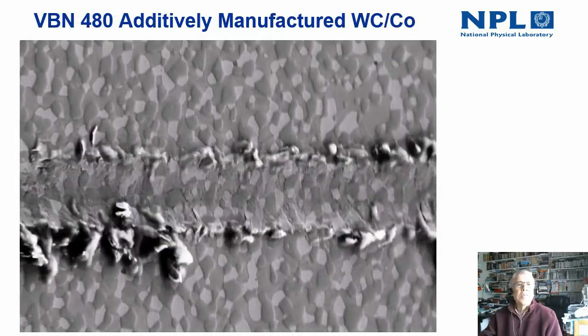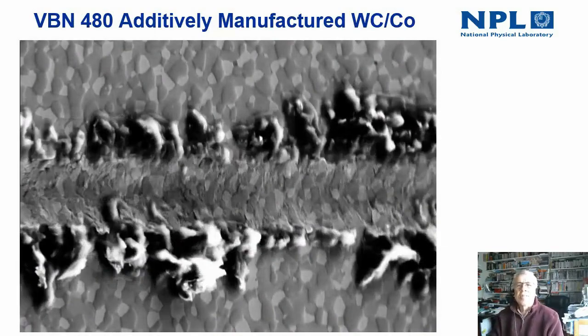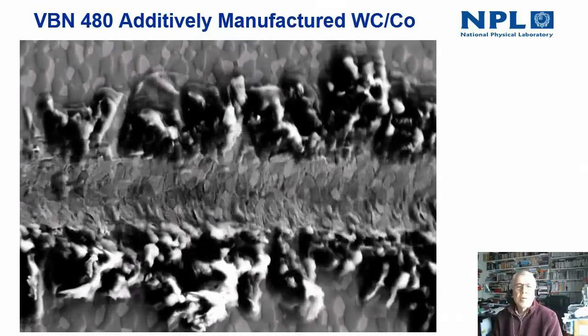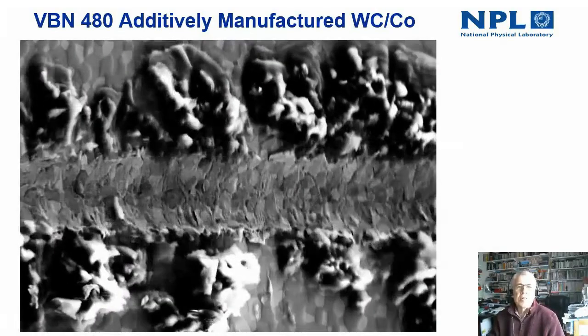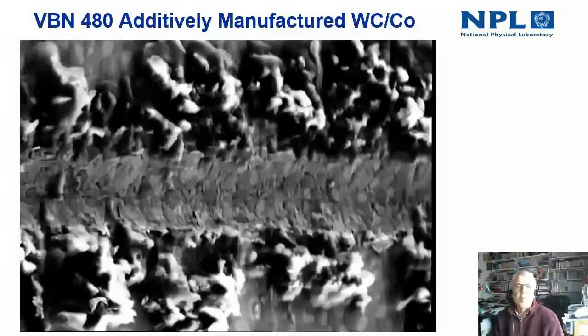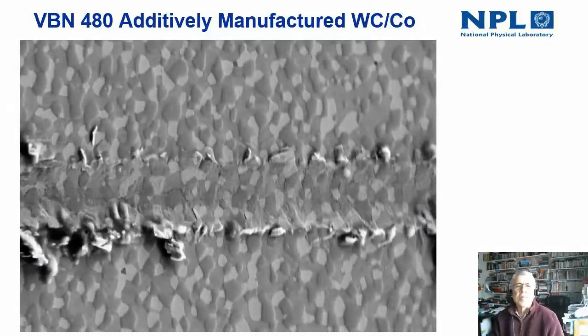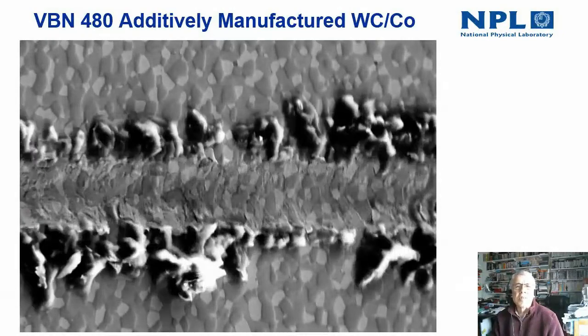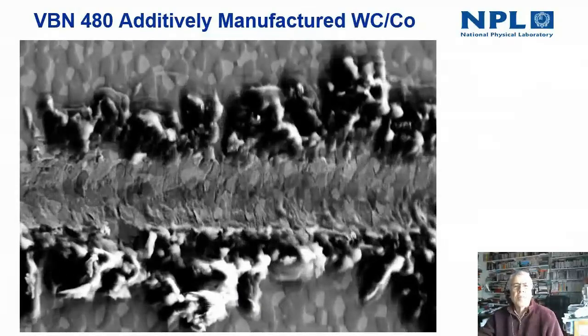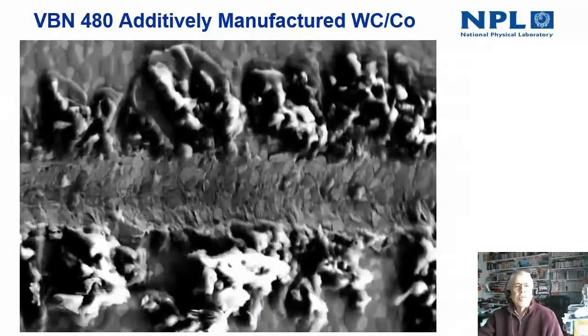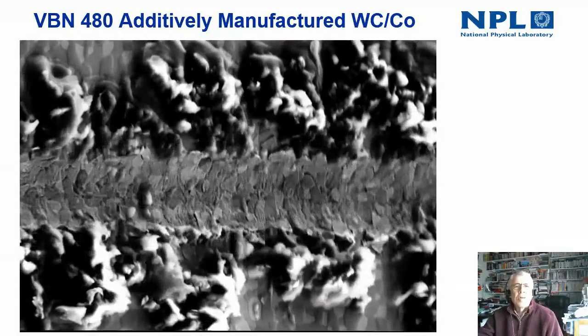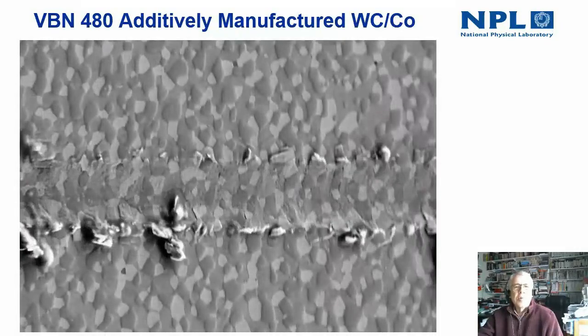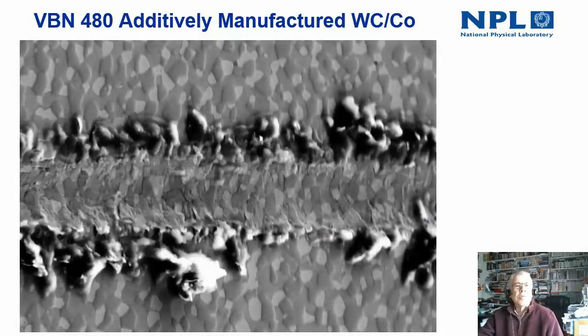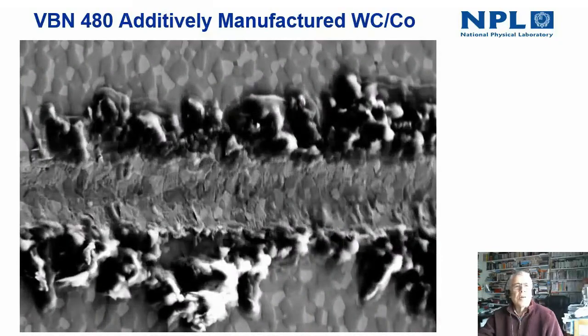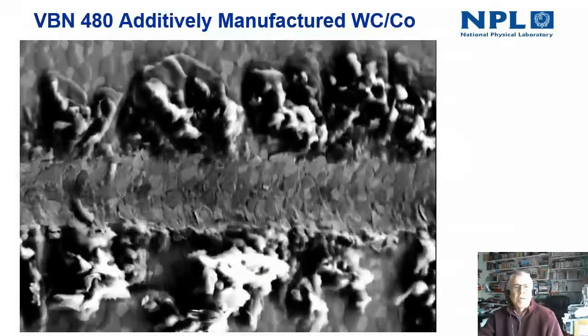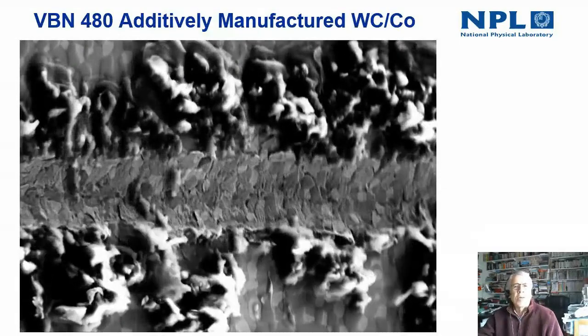This example is a VBN 480 additively manufactured tungsten carbide cobalt material. You can see how the damage occurs at the base of the scratch and the relationship of that with the microstructure of the material. So again, you've got slip lines, you've got cracking, you've got all sorts of damage occurring there. And also, interestingly, you've got these areas where material is pushed out to the side of the scratch itself and eventually delaminates from the surface and is removed. This work was carried out in a collaboration with the University of Manchester and the manufacturers of the material itself, VBN Components.